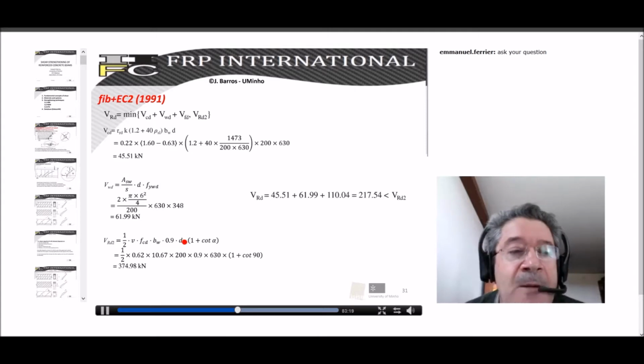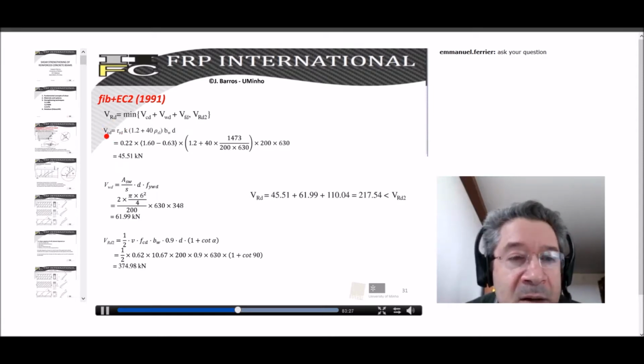We start evaluating the contribution of the concrete, and according to EC2, we obtain a value that is about 45 kilonewtons. For the steel stirrups, taking into account the spacing between stirrups, that is 200, and considering that we are using stirrups of 6 millimeter diameter, and with a design value of the yield stress of 348, we obtain finally a value that is about 62 kilonewtons.